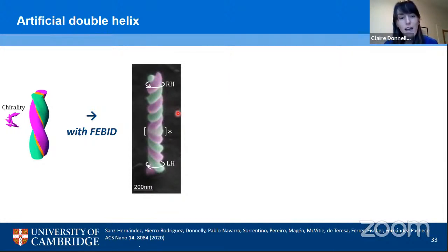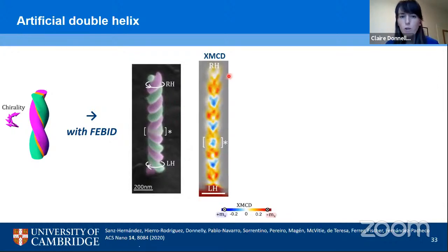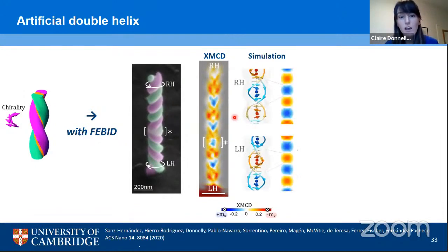helix structures. And what we first of all want to do is see what the magnetic configuration of this structure is. So we go to our X-ray magnetic circular dichroism again, and this time we're going to the Mistral beamline at the Alba synchrotron, where when we look at our XMCD images, we see a quite clear signal or pattern. We see red, then blue, then red, then blue, so this alternating contrast along the long axis of the helix. And when we compare it to micromagnetic simulations, we see that this actually corresponds to the anti-parallel alignment of the helices.